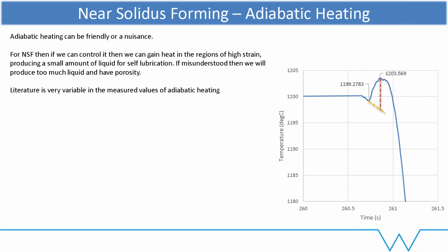It's a very, very hard thing to measure adiabatic heating. And in literature, you can see that there's values somewhere between 10% and 90% of the energy is turned into heat. So we need more precise values than that.